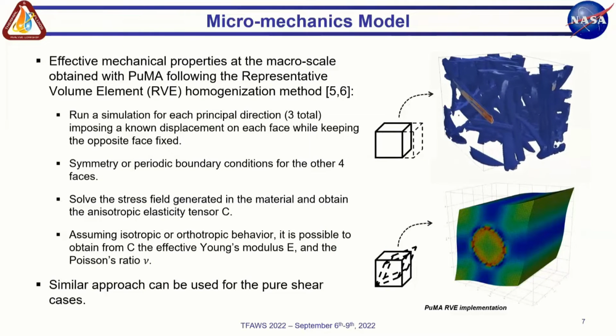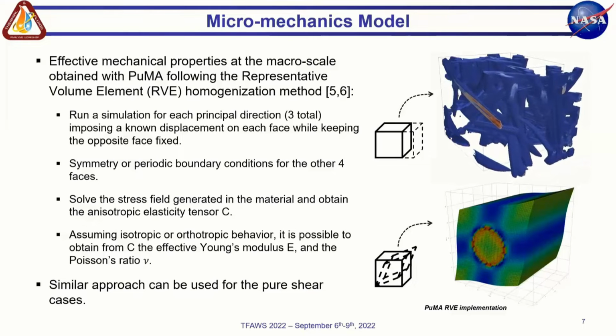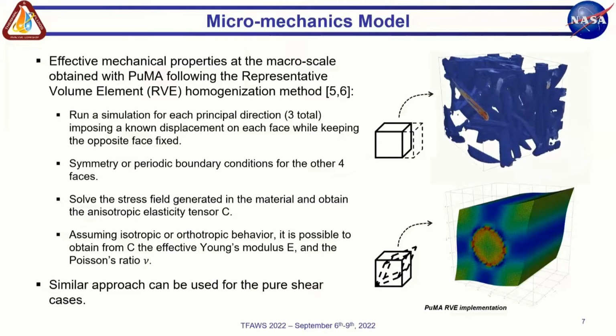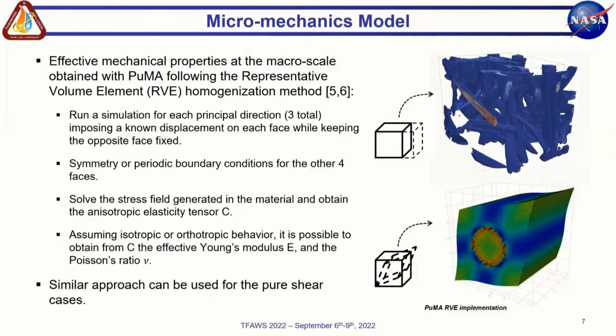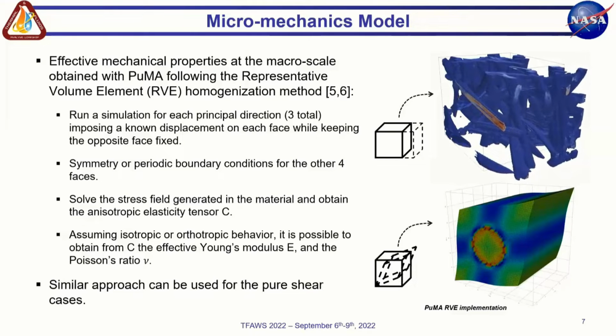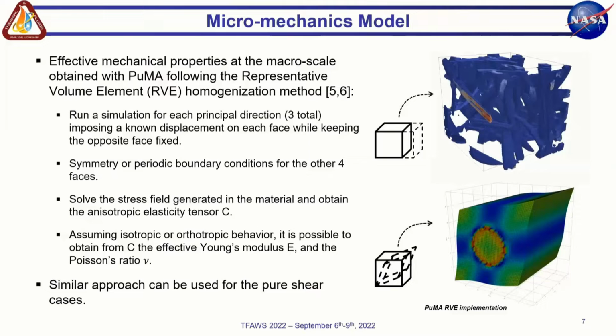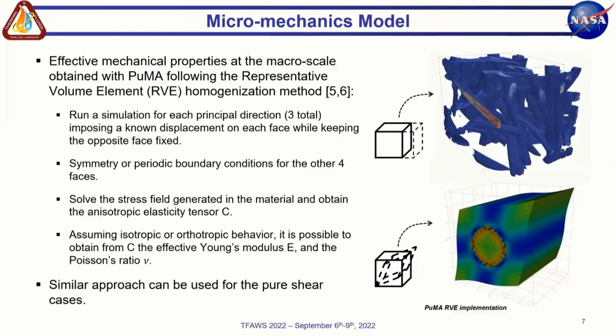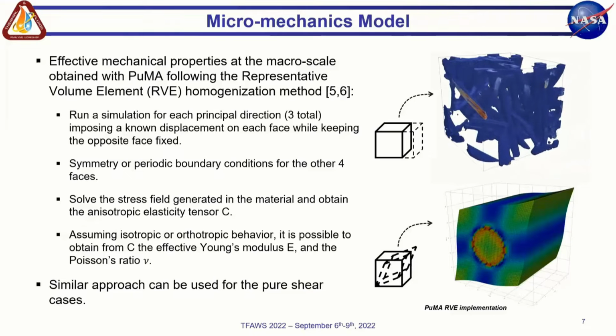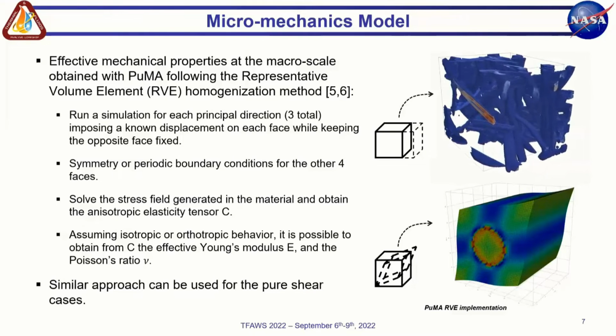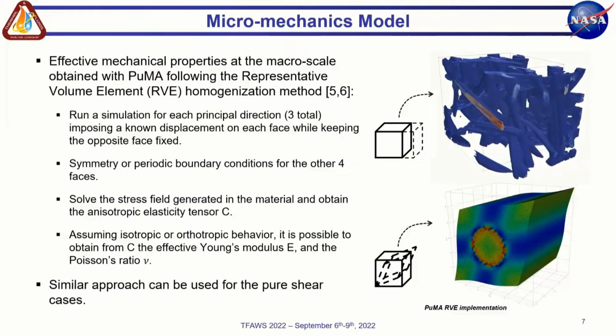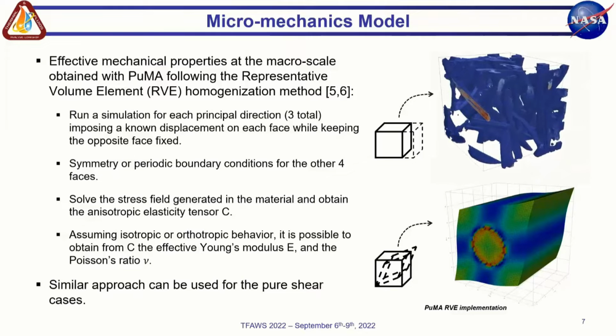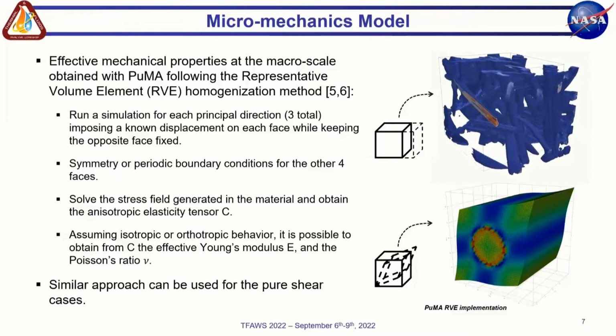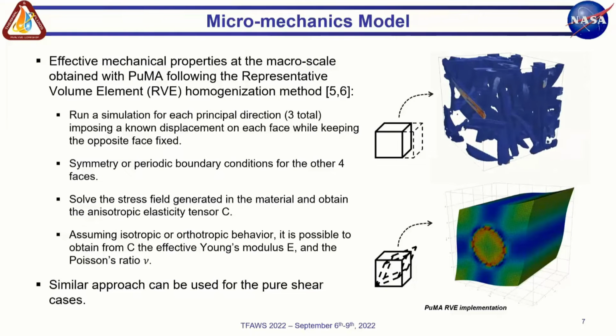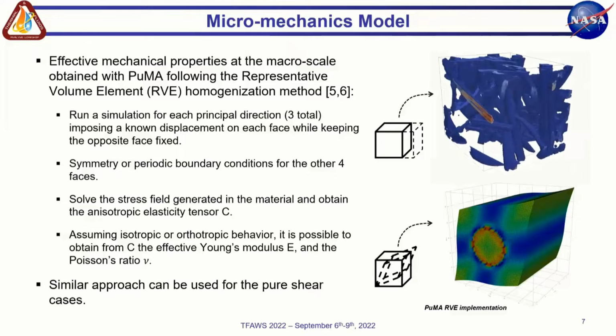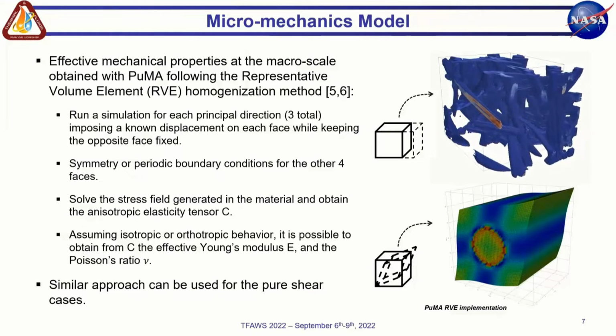Using this solver, the effective mechanical properties at the macro scale can be computed following the representative volume element homogenization method, which consists of running a simulation for each principal direction, so 3 in total, imposing a known displacement on each face while keeping the opposite face fixed. And then we apply symmetry or periodic boundary conditions to the other 4 faces. After that, we can solve the stress field generated in the material and obtain the anisotropic elasticity tensor C. Then, assuming that the material is isotropic or orthotropic, it is possible to obtain the effective Young's modulus E and Poisson ratio from the C tensor. A similar approach can be used for the pure shear cases to obtain the shear modulus.